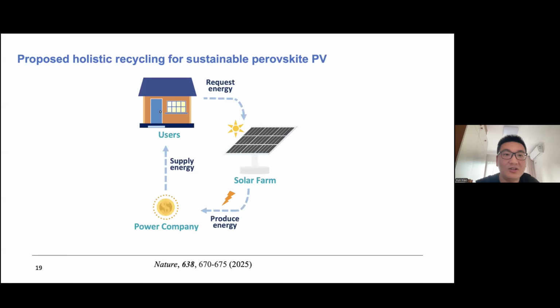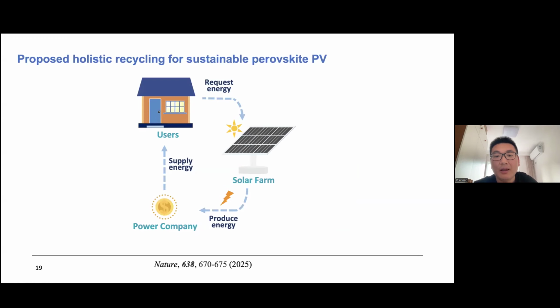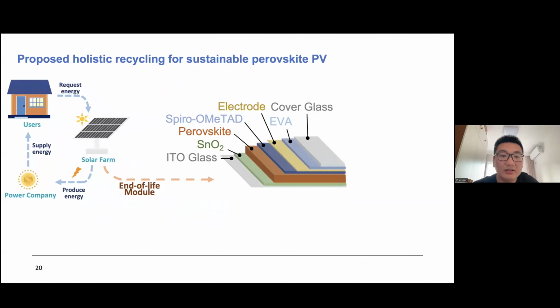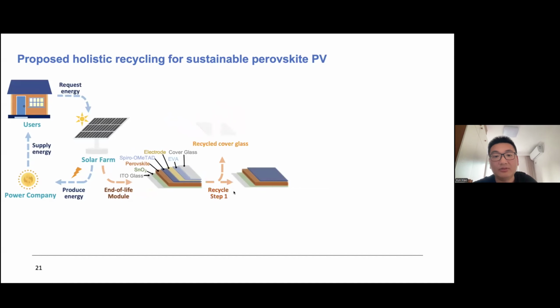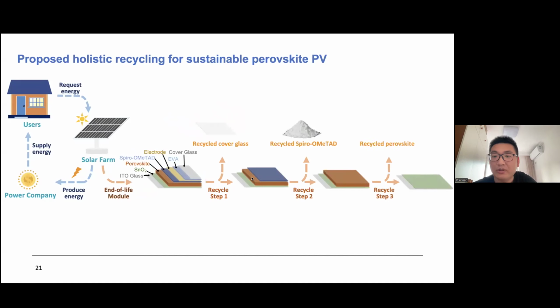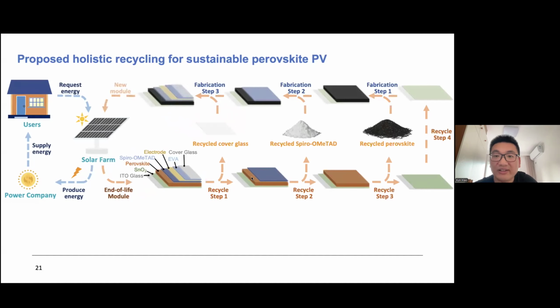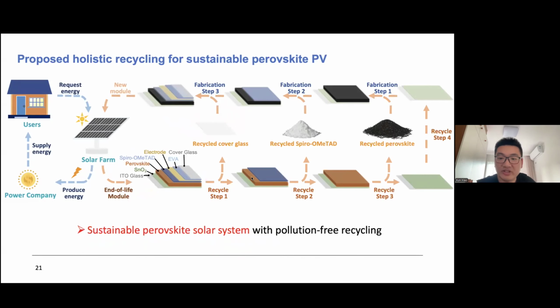So this comes back to the topic that was presented before, that we propose holistic recycling for sustainable perovskite PV. We want the perovskite solar farm to produce energy for the power company and then supply energy to our society. And this society will consume more energy. But when the solar farm is at the end of life, the degraded perovskite solar panel, like this one with this layer-by-layer structure, can be recycled layer by layer. What we are trying to do is recycle the cover glass, the perovskite, and then the tin oxide and also the ITO glass. And then we use the recycled materials to build a new module with a pollution-free recycling process. We want to make the whole process pollution-free and high efficiency.